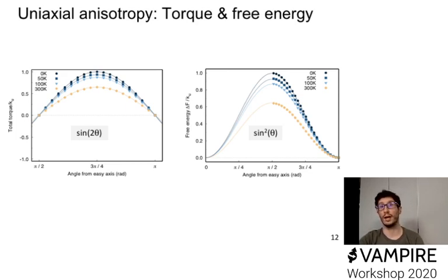This gives you the energy value substantially, which, because the main contribution here is the anisotropy, or actually in this case it's just the anisotropy, if we calculate the difference in energy between the maximum and the minimum, we will extract the anisotropy energy.